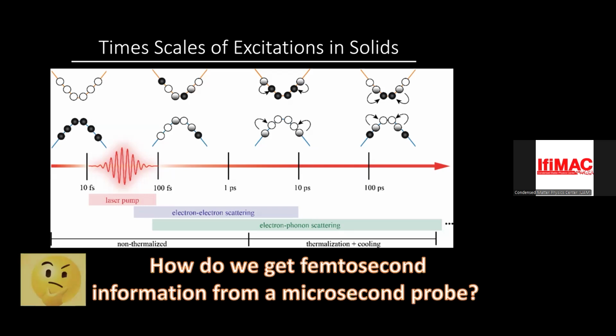The question is, how do you get femtosecond resolution from STM? And we all know that the STM is, sometimes very frustratingly, extremely slow. It takes us minutes to take an image. It takes us days to get the dI/dV map. At the best, you can get maybe microsecond time resolution if you try really hard. But to get picosecond or femtosecond time resolution is extremely difficult with the scanning tunneling microscope. They have these cables, they have capacitance. It takes time even for a signal to go from the STM to the top of the fridge. There are many constraints. So the answer is light.